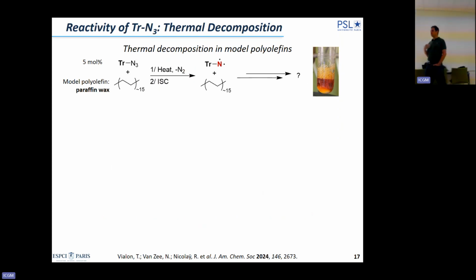And in our case, we did not know about the chemical reactivity nor the grafting reaction. So we performed model reactions, either with only the molecule or we used paraffin wax, which is a good model for PE. It's a very, very low molecular weight PE, it's not a material, it's a wax, but it's much easier to analyze. You can do NMR of this, you can do GPC of this. Of course, you can do NMR and GPC of HDPE, but it's a bit more challenging. So we use it as a model.